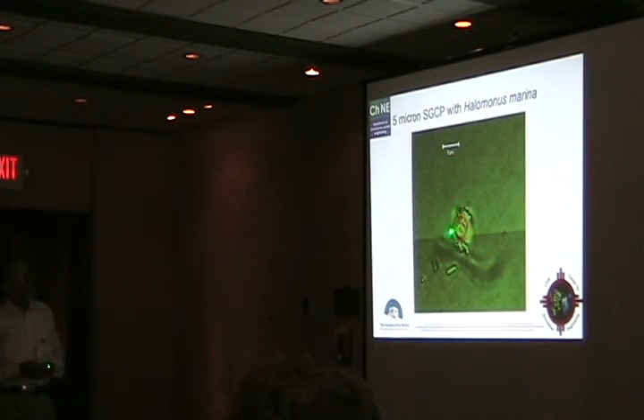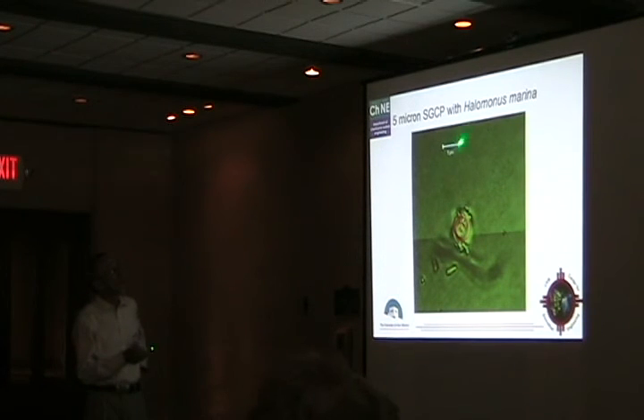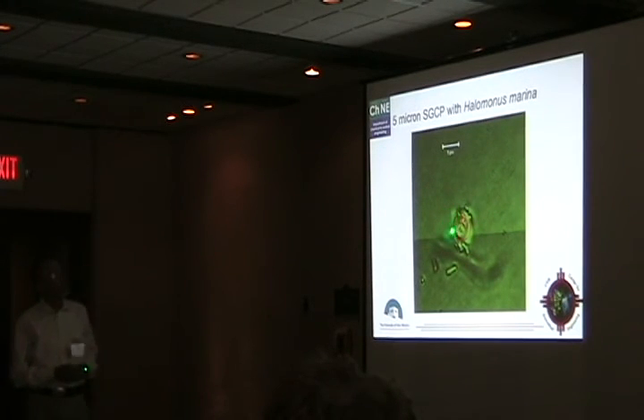And the most interesting thing is that these surface-grafted polymer beads sort of act like bacterial flypaper. If we just mix a small amount of bacteria with these beads, and these are again 5 micron beads. We've done some work with the 300 nanometer cationic beads, but what you can see is there are a number of bacteria associated with the bead, even at fairly low levels of the beads and fairly low concentrations of bacteria. We've seen some of this on flat surfaces, but it's really dramatic in these cases. And so what we've done is to actually study the bacteria with these 5 micron beads and look at the biocidal activity in some detail.